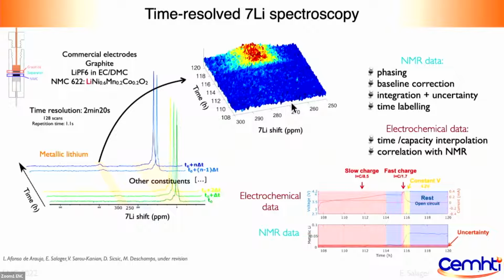And this is not discussed a lot, but actually here there are a lot of steps with approximations that you do. And so of course we had to phase the spectrum every time because we want to charge the battery quite fast, in 15 minutes. So we don't have time to tune it every time. Even automatic tuning is too long. So the tuning changes slightly and the phasing as well. So we had to rephase every spectrum independently.